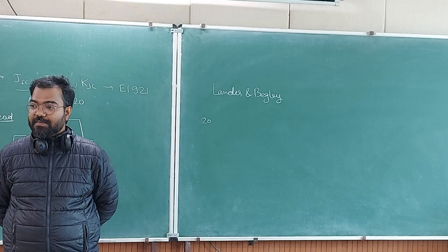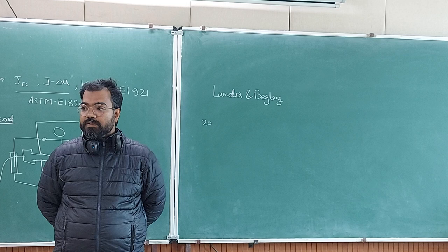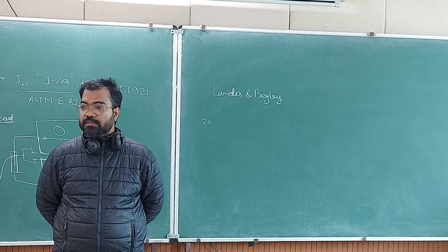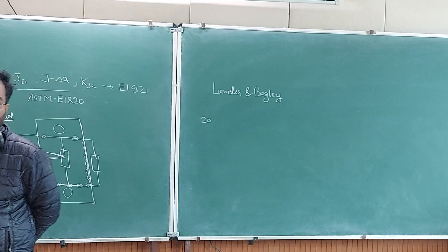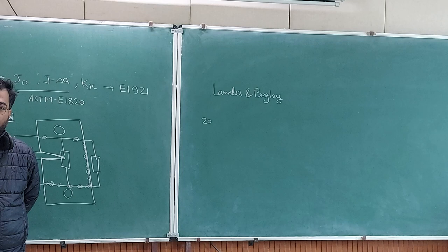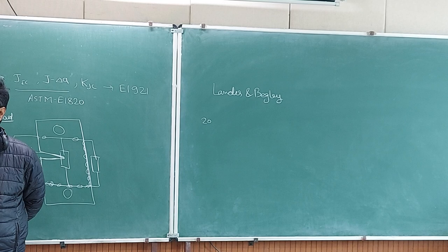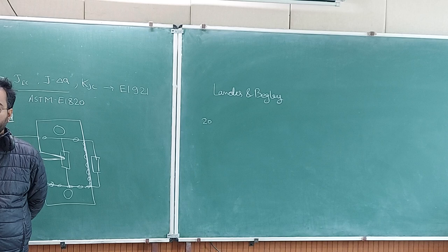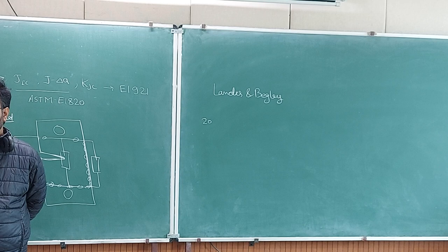So steel, whether it is made from a basic oxygen furnace or LD furnace or electric arc furnace, whatever furnace you are using, and then you are doing secondary refining, the final processing after that, is one heat. Each heat can have different composition, a little bit of variation, so you will have chances of changes in property because of change in the heat. Let us say your furnace is of 20 ton capacity, so that 20 ton is supposedly homogeneous. Also it depends on cooling, surface will have different properties, center will have different properties. But more or less it will be the same.